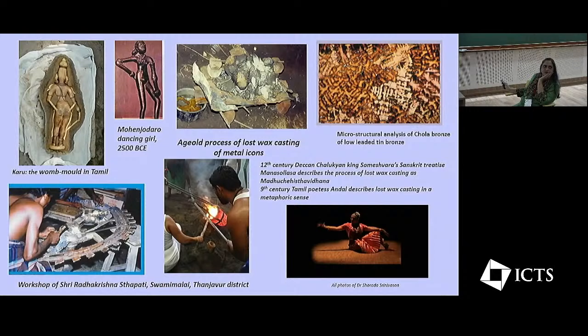I don't know how many of you here have a background in metallurgy, but quite simply, the microstructure refers to a small sample of the metal artifact being taken and then being polished and mounted and observed here under an optical microscope, but then you can also look at it under scanning electron microscopy and so on. So this is in fact a sample of a Chola bronze which I had examined under the microscope. And as you can see here, it's a very typical structure which gives away what the composition is, which is basically a low leaded tin bronze. And you see these typical dendrites, which are formed from the as-cast process, these fern-like structures, which we call dendrites.